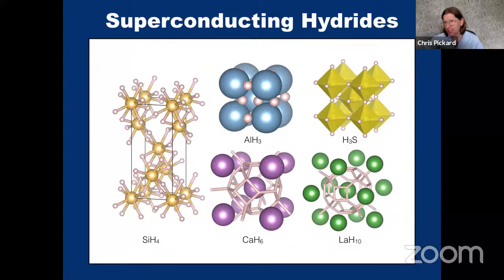kept going, and also Defang Duan and Tian Cui, also in Jilin University, kept going and were making different suggestions. So Yanming Ma suggested hydrogen sulfide could be a high temperature superconductor. Defang Duan and Tian Cui also studied precisely the H3S composition, and computed the TC for H3S to be about 200 Kelvin. This was in advance of experiments that Mikhail Eremets did, which actually did find superconductivity just above 200 Kelvin in the hydrogen sulfide system. So this was a big moment. I remember where I was when I heard that result, and it very much got me excited again about this field.